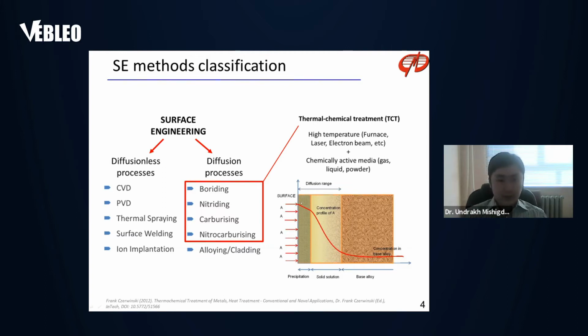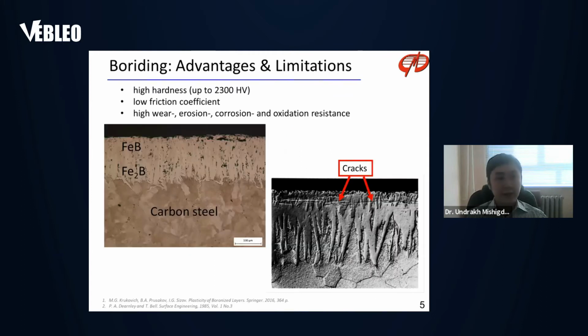like here. And among TCT methods, boriding is capable of providing many attractive properties, such as high hardness, low friction coefficient, and high wear, erosion, corrosion, and oxidation resistance. As a result of treatment, a tooth-like microstructure consisting of FeB as an outer phase and Fe2B as an inner phase layer can be obtained.